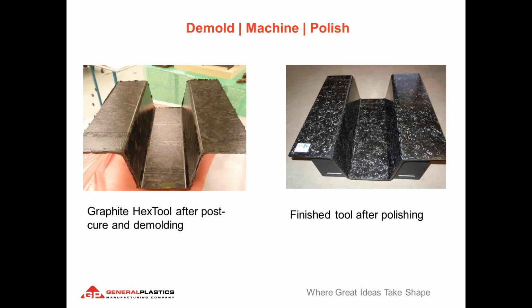So again, the demold of the materials. This is the Graphite HexTool. This is from the tooling surface. You can see the seams overlapping from the Tool Tech tape. And this is the resin-rich surface, and typically best results are seen when you remove that resin-rich surface and expose the fibers below. This product is recommended to be machined after cure. About 60 thou of material is removed to show this nice marbly finish that's been polished and is now ready for use.